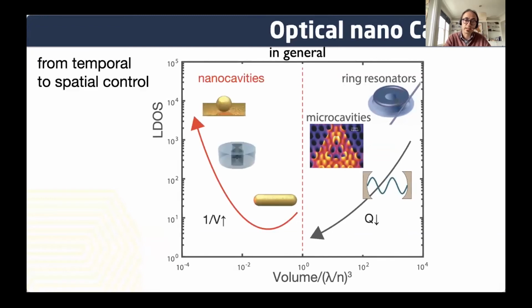But if you go on the smaller side, there is a moment that you cross the red line, which is the wavelength of the light. And when you go to the nanoscale, then suddenly you can design structures that instead localize a field into smaller and smaller volumes. So you lose the temporal control, you gain spatial control. And when you do that, you are enhancing the optical interaction by basically squeezing the light into volumes smaller and smaller, closer to the size of your dipole, which is always of the order of nanometers. And so in this way, you can see that this curve goes up again, and the Purcell enhancement can be very high. And this is the regime, of course, where we are interested to work.